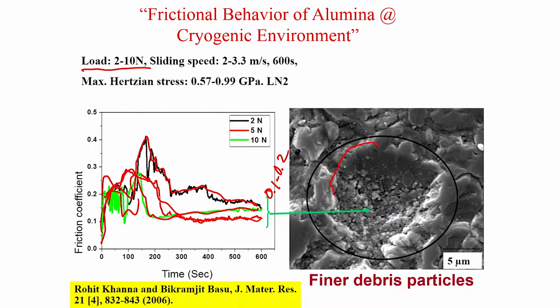Looking at the wear surfaces, you can see extremely fine debris particles — these are alumina wear debris particles. What happens during sliding wear at high speed conditions is that these alumina grains are crushed into finer debris particles, and as a result these debris particles essentially lead to a three-body wear situation. This is fairly important to recognize: in the case of self-mated ceramics it is three-body wear that can potentially take place and lower the coefficient of friction as sliding progresses.